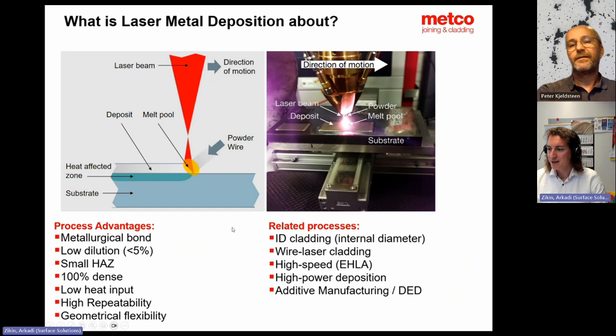Yeah. So basically, in simple words, if I put a very expensive material on top of a cheap mild steel, and it's a 50-50 mixture, it means in the first layer only 50% of my material properties remain, and 50% will go to the substrate, and also 50% of the substrate is going to penetrate into my, let's say, coating. That means I need to build multiple layers till I get a pure coating. But as we also know, if we put multiple layers, there might be more heat input, and you can cause other problems like thermal shock, crack propagation, and so on, depending, of course, on your case.